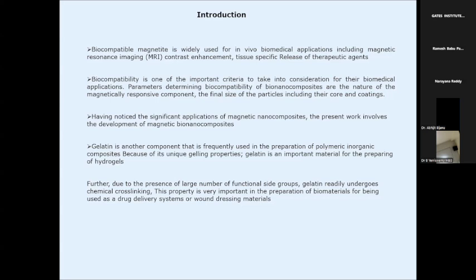Which will go through chemical cross-linking. So see, as I said in the beginning, a hydrogel itself is normally a cross-linking polymer. So when you have a cross-linking polymer, and you are using acrylamide, some cross-linking polymer, and your gelatin also has cross-linking nature, it will start to build a big cross-linking network. So the capacity for holding the nanoparticles inside the hydrogel is also very big. Simultaneously, it will hold the nanoparticles in a proper size. So you will get both the advantages.